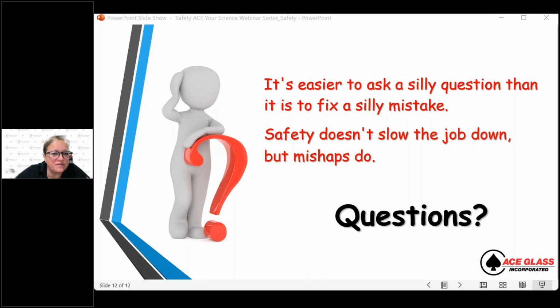If glass is fogged up from hot alkaline reactants, is that permanent or can it be fixed? No, unfortunately, that is pretty permanent. That is when you have a compromised crystal structure. Basically, you have enclosures or gaps in there that cause that visual effect on it. If your glass does start to look foggy or blind, then actually the damage is already pretty high and you really want to get rid of that.